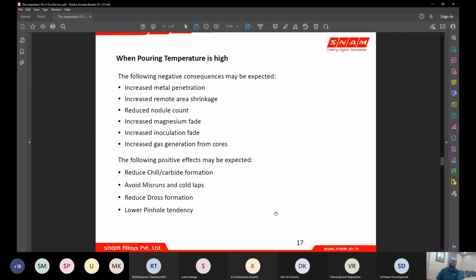There will be more gas generation from the cores, because you are going to superheat the cores, and you are going to keep the cores hotter for a longer time. The rate at which gas generation from the core occurs is aggravated when you keep the core at a very high temperature. That means if you heat the core at a very high temperature, or for a longer time at a very high temperature, gas generation is going to be more, and the rate of gas generation is going to increase, and because of it, you may end up getting gas defects.